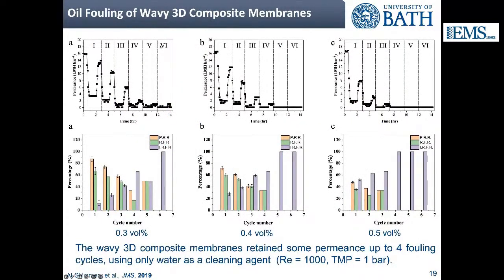So we then did, if you look at the top left plot, we actually did 6 fouling cycles: pure water, oil and water, and then switch to pure water to clean. And you can see with the wavy membrane, we managed to get some permeance until about the 4th cycle, after which the membrane is fouled. Remember that with the flat membrane, you lost everything after the first cycle. There was no permeance after the first cycle. At the bottom ones, these are the components of reversible and irreversible fouling. It's more or less what I already mentioned before. You can find more details in the paper below.